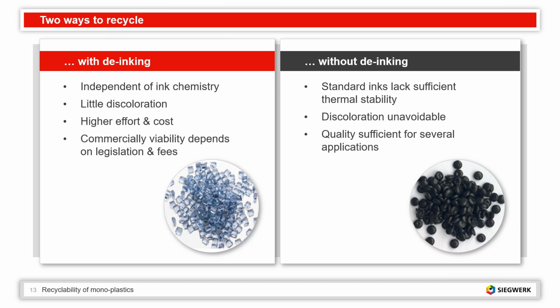And if you look at the left-hand side, what are the advantages of de-inking in this process? It is certainly that we become independent of the ink chemistry because you wash it away. Because no more pigments are available, there's also less or hardly any discoloration, which is a benefit. Of course, the de-inking process would bring a higher cost or higher effort because it's a process which is not yet established in the industry on a wider scale. And on this background of higher cost, the success of this way and also the implementation in the industry will certainly depend on legislation and developments there, in the sense that only by some fees in favor of packaging material which would be de-inkable, you could develop this de-inking process.